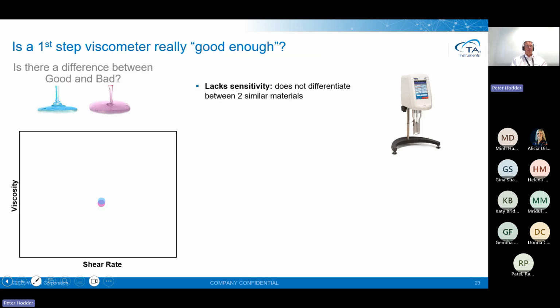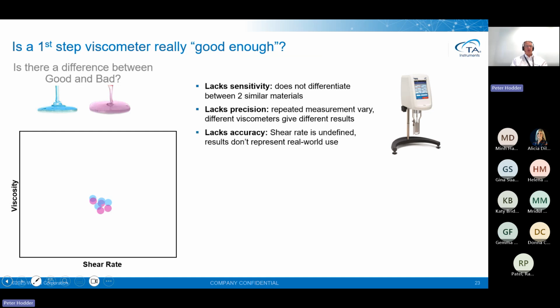Now, take this a little bit further. If we take an example of two materials, one known to be good and one known to be bad, the good one is blue, the pinky one is bad. What we see is, if you do a measurement, a pragmatic approach at one speed, you basically get very similar answers. You can't really see a great reproducibility because the numbers are all over the place. And then basically, because you can't define shear rate, you can't really represent it to a real world thing. So what we've got is a comparison which is more or less a random number generator.